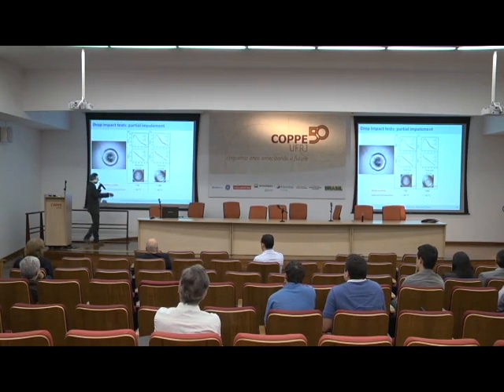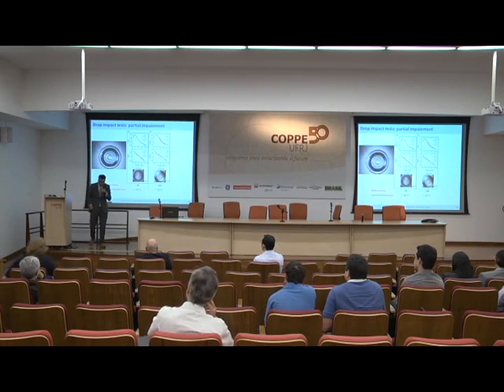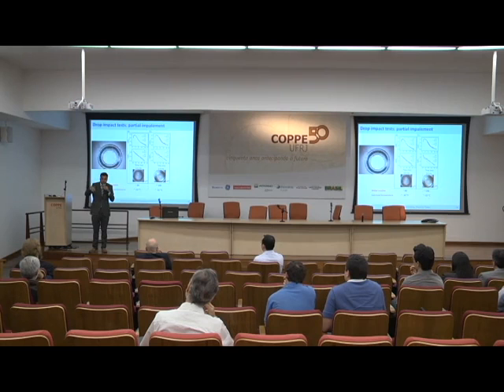And what's happening is, if you see at the center here, we start to see some pattern emerging. What I think is happening is at the center, where the pressure peak appears, some of the liquid goes into these micropillars, and then the contact area changes. And when that changes, the contact time also changes. That's the point where the failure occurs, because that's the point where the maximum pressure occurs.